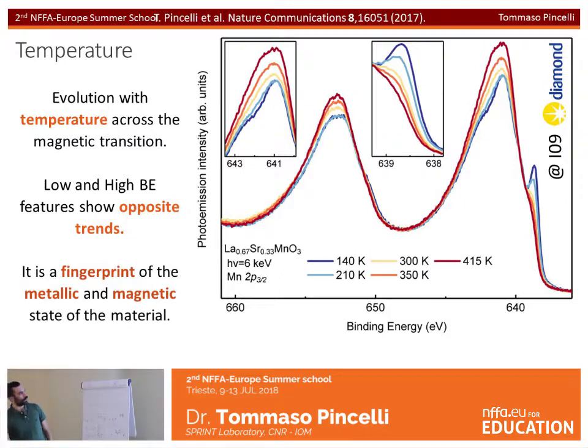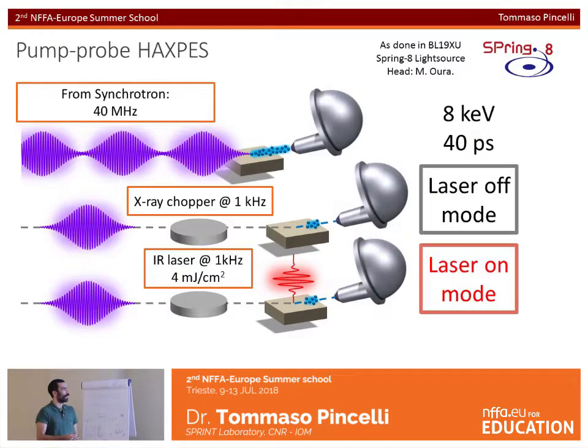How can we do, though, time-resolved photoelectron spectroscopy with hard X-rays, because we are using 6 kiloelectron volts or 8 kiloelectron volts? Well, there is basically only one place in the world that does it. It's a beamline at SPring-8. So they use the pulses of the synchrotron that come at 40 megahertz and 8 kiloelectron volts. They have a duration of 40 picoseconds. And then they chop them down to match the repetition rate of the laser.